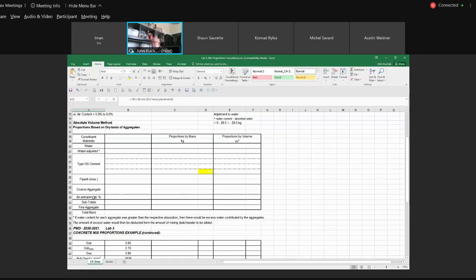I'm not using any water reducers in my mix. And when we talk about admixtures, you'll understand why most ready-mix producers use water reducers. It's exactly what it says. It can reduce the amount of water. The water reducing admixture will reduce the water content. If you reduce the water to maintain your water cement ratio, you can reduce the amount of cement. Or you keep the cement where it is and reduce the water demand, because the liquid admixture is going to give you your slump, your flow. Now you've increased the strength because you've reduced your water cement ratio. You kept the cement where it was, but you dropped the water. So now instead of having a 0.45 water cement ratio, maybe you've got 0.40, depending again on your water reducer.